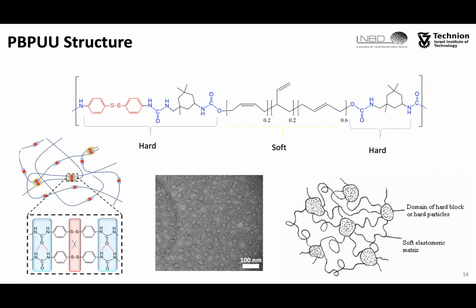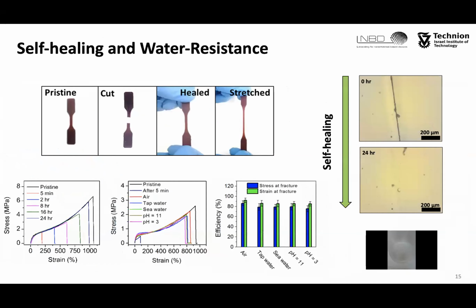The simulations briefly show that water molecules can only interact with the hard regions, and they barely diffuse into the soft regions in the new self-healing polymer. The hard regions don't form a continuous pathway into the polymeric bulk, and therefore, overall, this could explain why these polymers are not sensitive to water, reaching our ultimate goal which we designated beforehand.